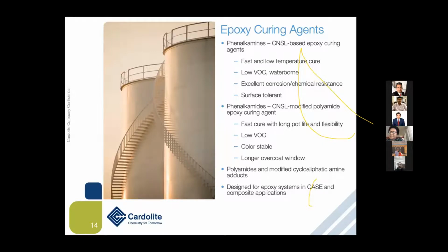Now, yesterday we had a presentation, a beautiful presentation by Dow. And I remember there were some queries of single pack water-based systems. So let me tell you, we have these waterborne systems as well, which though the products have excellent water resistance, we've come up with waterborne products out there. So we have phenalkamines, which are waterborne as well, and which are completely water resistant as well. From phenalkamines, you get excellent corrosion protection, chemical resistance, and the best property is surface tolerance. So even if your surface preparation is not up to the mark, there is a little bit of rusty substrate out there, it still gives you very good adhesion. So failure mode is very less.